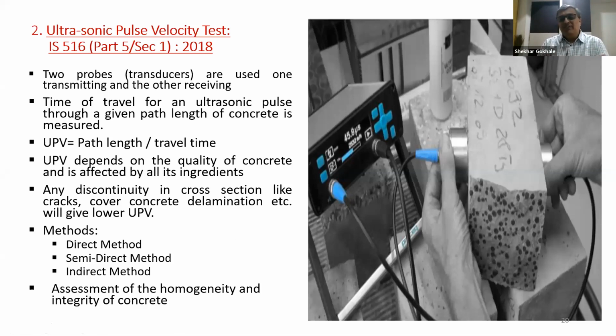And if only one surface of the concrete member is approachable, then we have to use both the probes on only one side, and that is called the indirect method. But the direct method gives a better reading, and in the indirect method there could be a variation of about 5 to 20%. So while taking the readings, as far as possible, we should use the direct method where probes are on the opposite side of the member. This gives basically the homogeneity and integrity of the concrete. It doesn't give the grade of concrete, it gives the quality of concrete, whether it is excellent, good, doubtful, or poor, like that.